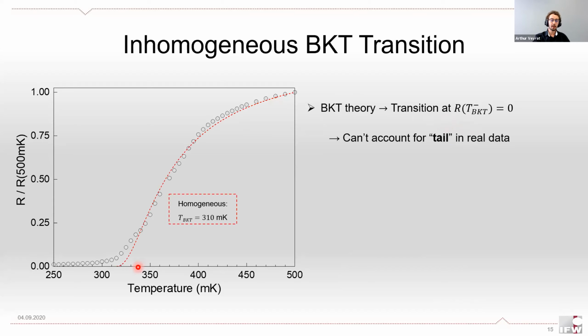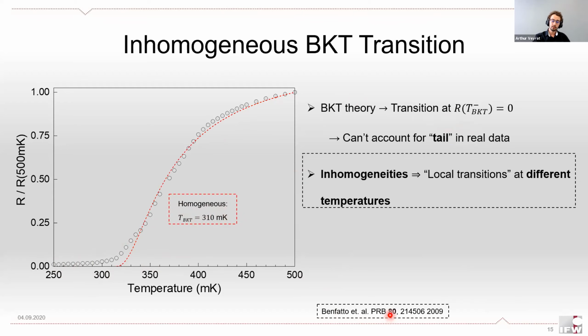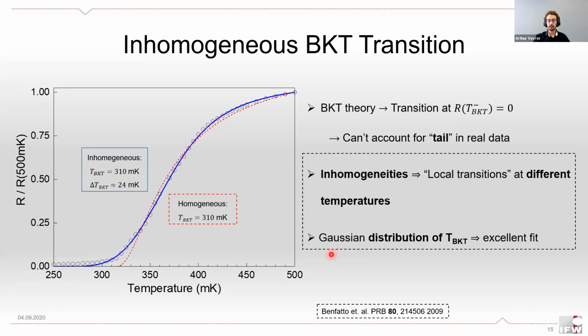So this is a fit using the Halperin-Nelson homogeneous model. As you can see, it is completely unable to account for the tail in our data, and that is actually because the BKT model, in a sense, is a homogeneous one. But according to this paper, we actually have to take inhomogeneities into account in real samples. We can think of inhomogeneities as if we had some local transitions happening at different temperatures at different places in our sample. To model this, we can consider, for instance, a Gaussian distribution of BKT temperatures and integrate the response over this entire distribution.